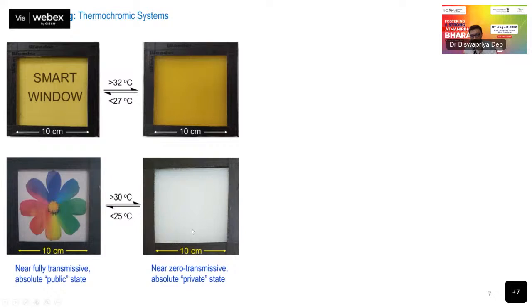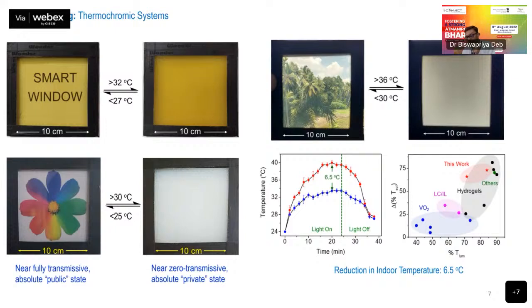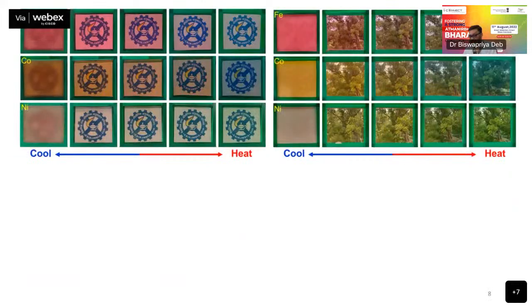Here you can see the device color is white, but you can use different dyes to make different color windows, and we already have several examples in our lab. As a benchmark, you can reduce the temperature by up to 6 to 7 degrees using this system. We also have metal or polymer based thermochromic systems, with different opacity at different temperatures. You can create various opacity levels using temperature.